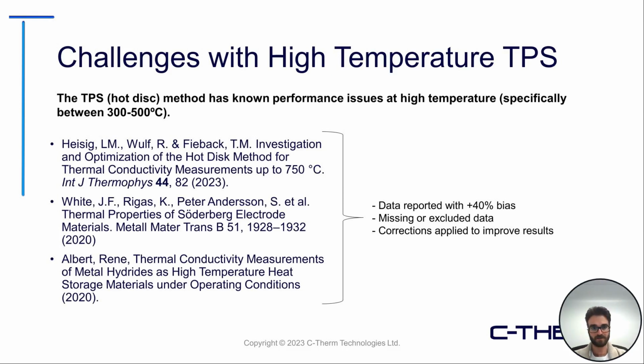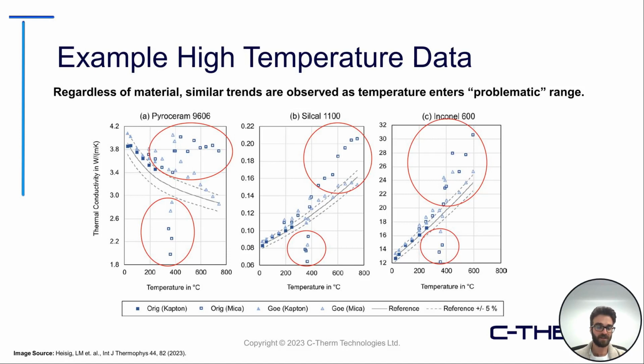But if you take a look in the literature, there is really a known issue, and it's been this way for a few years now, specifically between about 300 to 500 degrees Celsius, where people will note extreme bias in the high temperature results. Many papers will exclude the data or just simply not test in the problematic range, or they talk about corrections that need to be applied. So it's something that's been known as an issue by folks for a few years now. And this is just a data set I pulled from one of those papers referenced there. You can see the image source in the bottom, but it's really related to the sensor. So regardless of the material type, we're looking at a ceramic, a polymer, metal, different types of samples here. But you see similar trends as that temperature approaches that quote unquote problematic range in all cases.